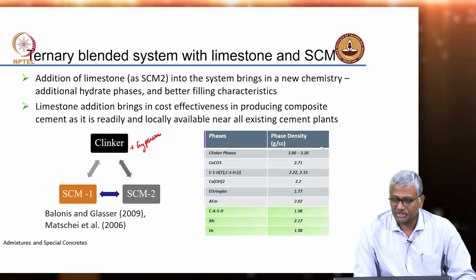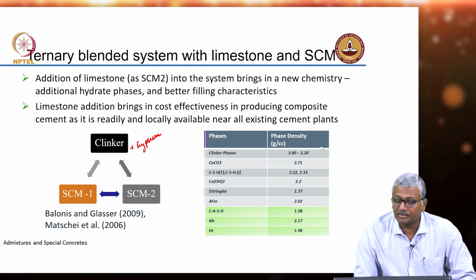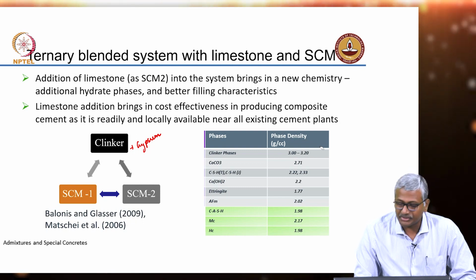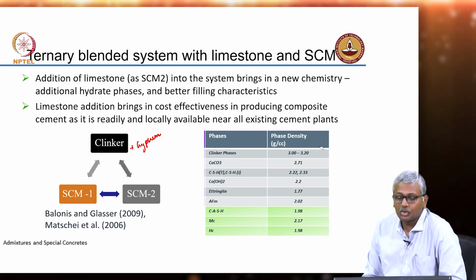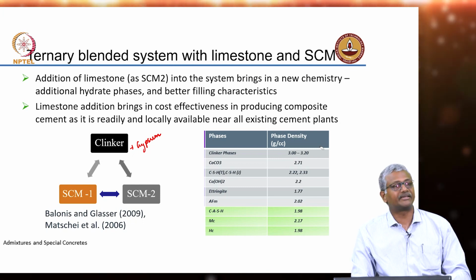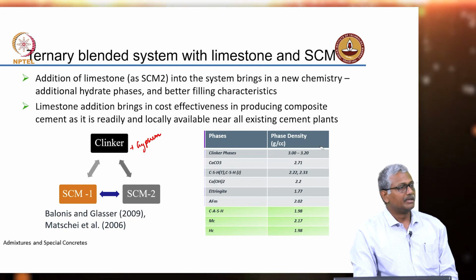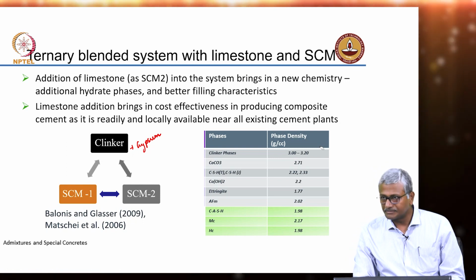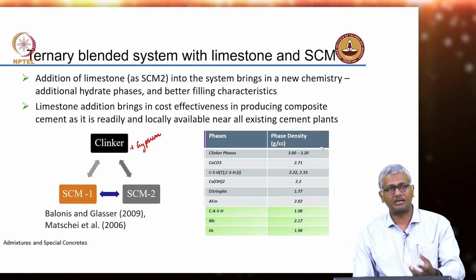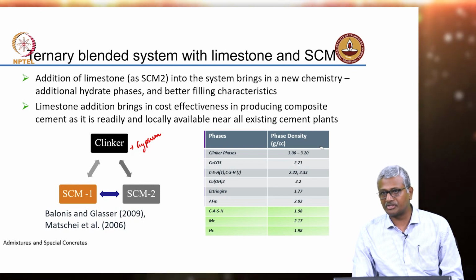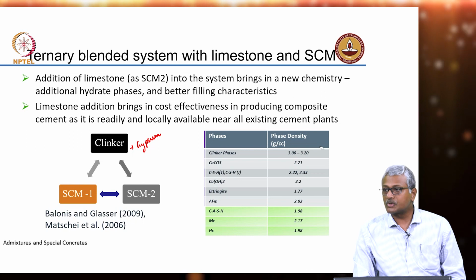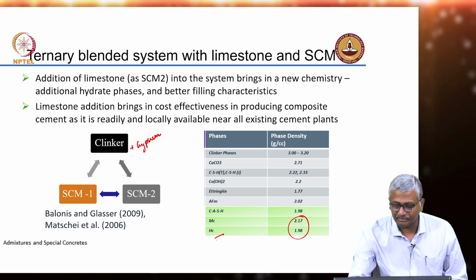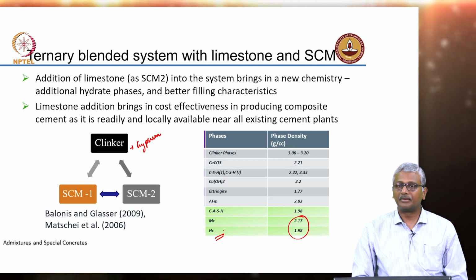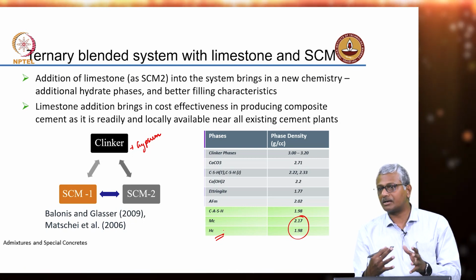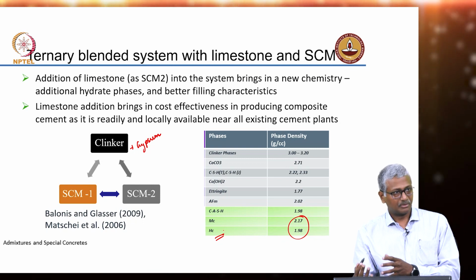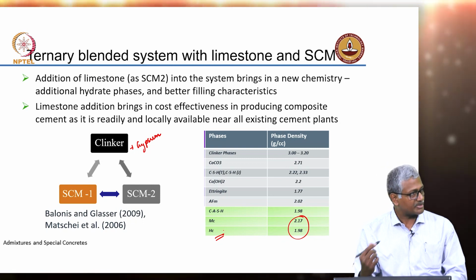Of course, I'll have CSH, calcium hydroxide, ettringite and monosulfate still. But I end up forming additional CSH or CASH by consuming calcium hydroxide. We talked about the fact that calcium hydroxide has a well-defined crystalline structure, because of which its volume filling ability is not that good. Although as a material, it's solid, it's hard and so on, but it's not able to fill up volume efficiently. Secondly, you also have the formation of additional hydrate phases, monocarbonate and hemicarbonate. So you are removing or reacting unhydrated phases to actually form these hydrated phases.